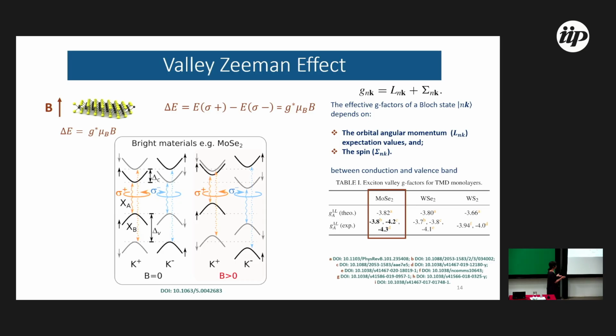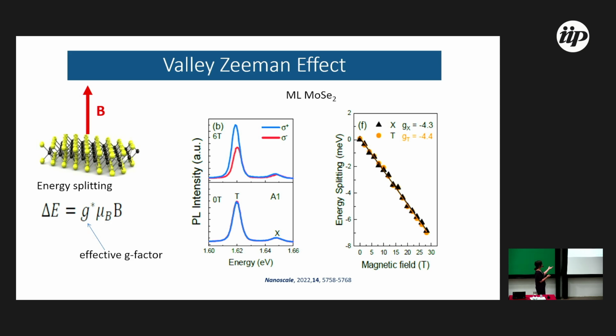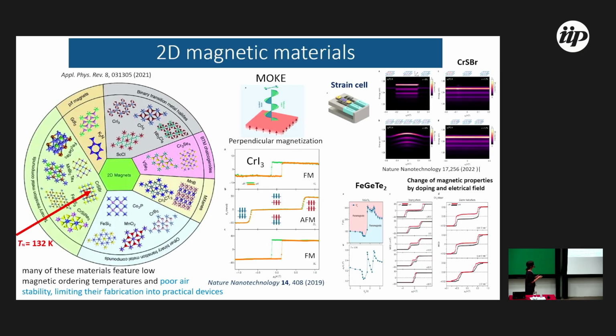So it depends on the bands involved in the optical transitions. People are used to measuring the circularly polarized emission, sigma plus and sigma minus, and you plot the difference of energy, the energy splitting, as a function of magnetic field, and you can extract these g-factors. This is important for me because I want to know what happens to these valley properties and exciton properties when you have these magnetic substrates.